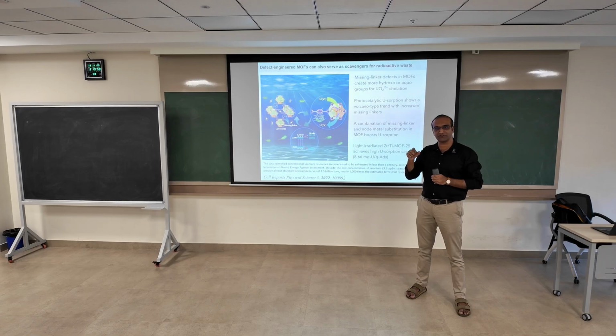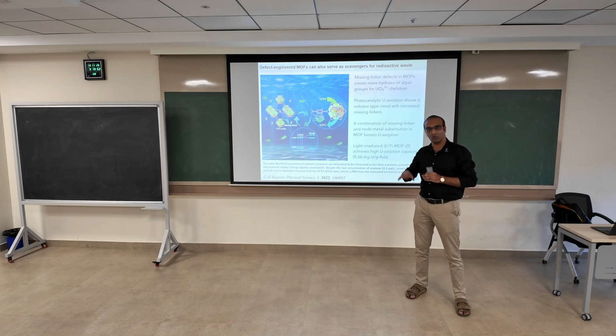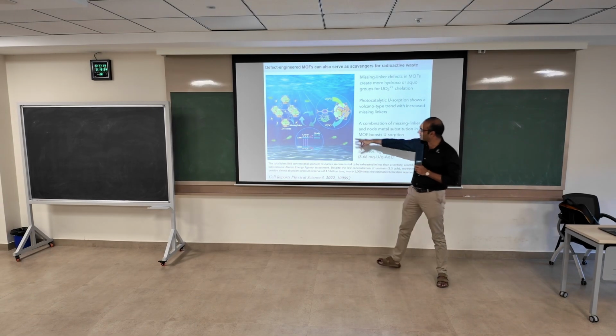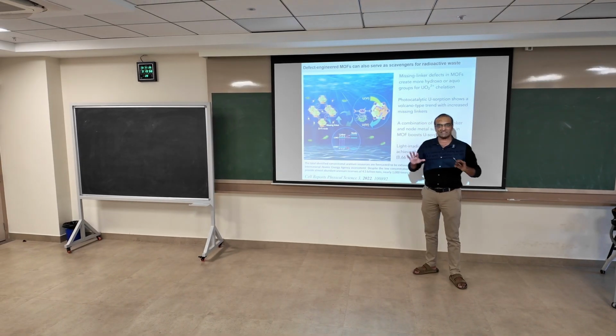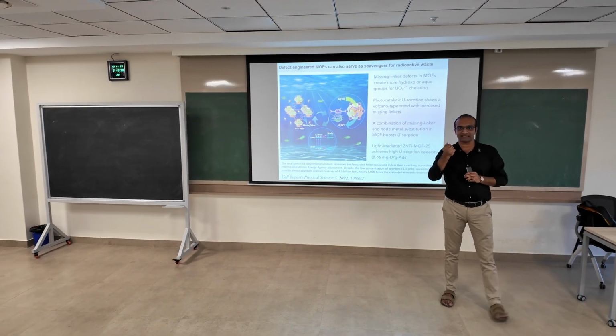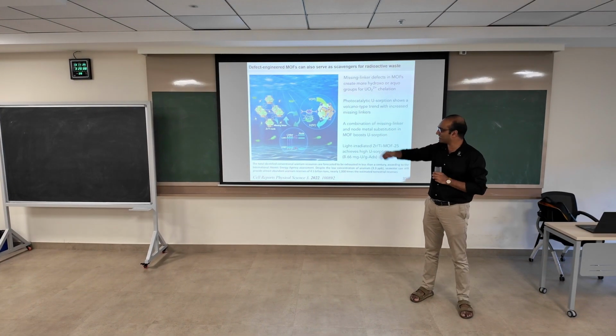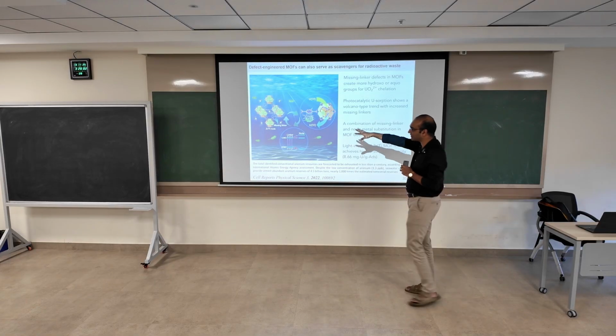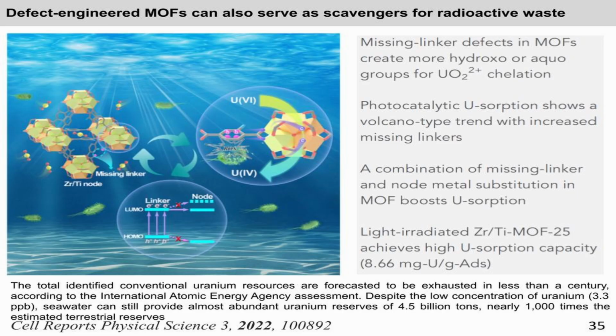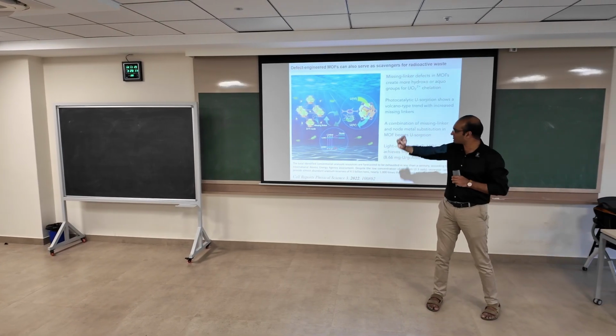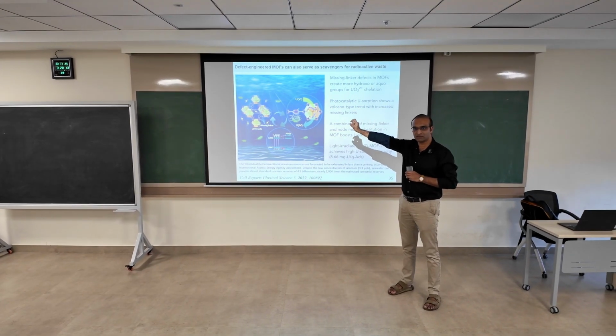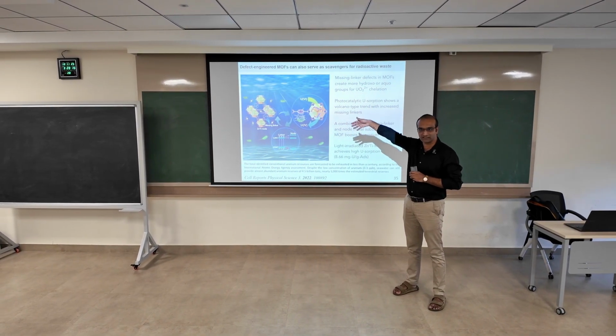Sometimes you can change the ratio. You can put less of the linker, and the MOF will still form, but you'll have these vacancies where the linker is missing. That linker site is called a defect. Here, for example, they mixed zirconium and titanium chloride. So you have a photocatalytic node and a spot where you don't have a linker, so energetics can happen through photocatalysis here.